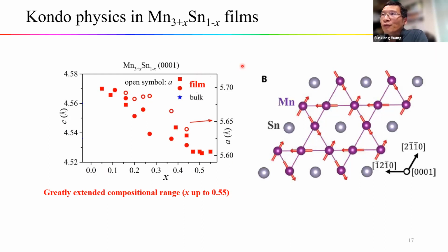Now, with those films, the epitaxial thin film is not just the same counterpart of the bulk materials. Because of the non-equilibrium nature of the fabrication process, we can actually get much more than just the same counterpart of the bulk materials. So as shown here, if we write the composition of the manganese-tin film in this formula, the x represents how many tin atoms are replaced by the manganese atoms.